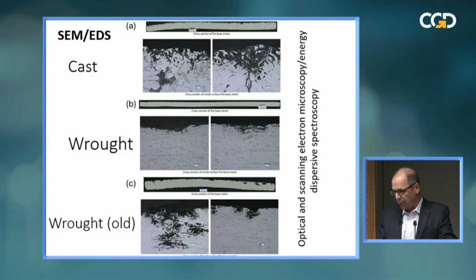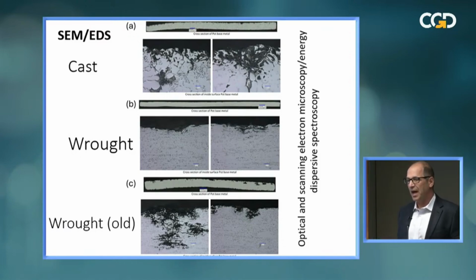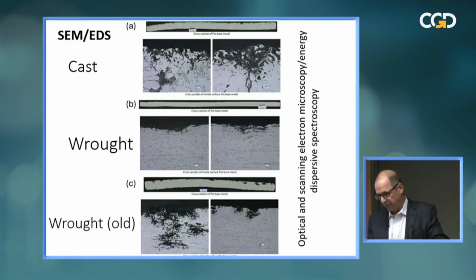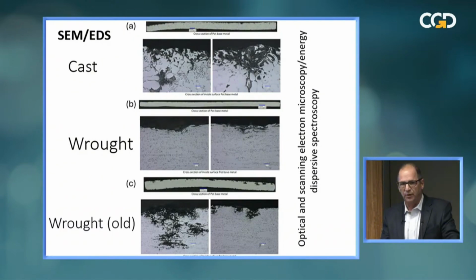Okay, and then you have the acetic acid attacking the aluminum. And again, these are cross sections, and they're forming in very different patterns. And so the cast versus wrought, I think that this, particularly with the wrought, the layered nature of it does impact the amount of lead that can leach out at any given time. And as the aluminum dissolves, it does it in preferential pathways.